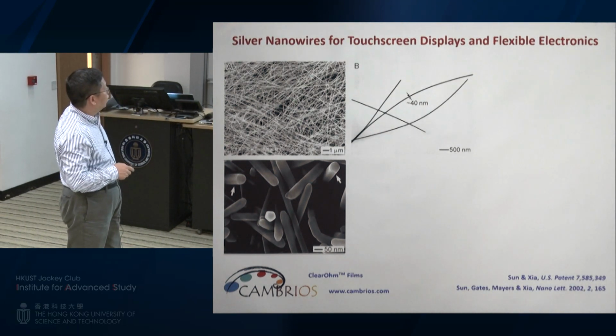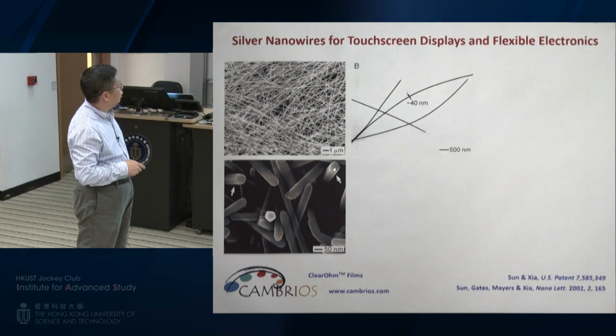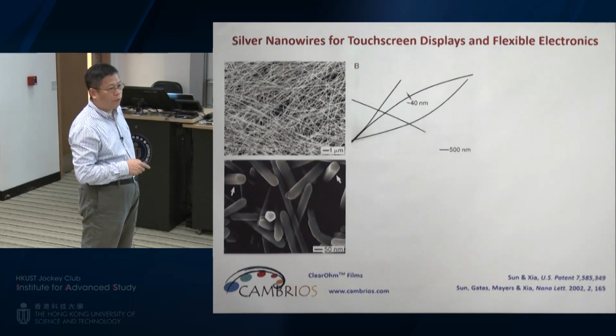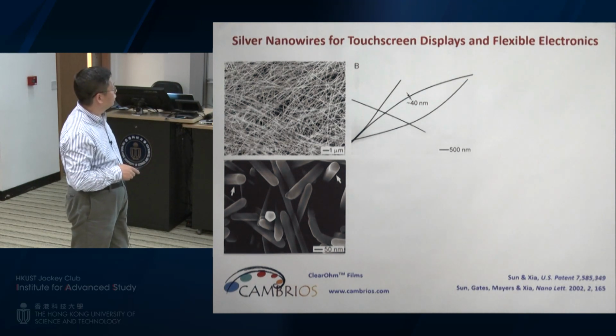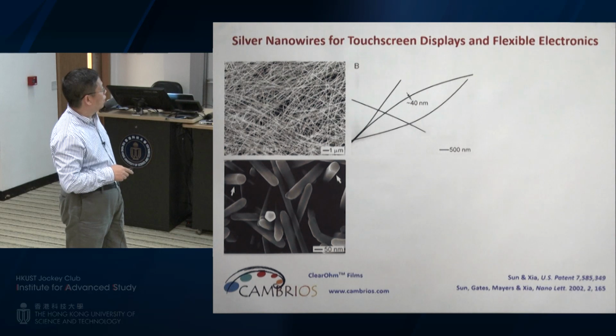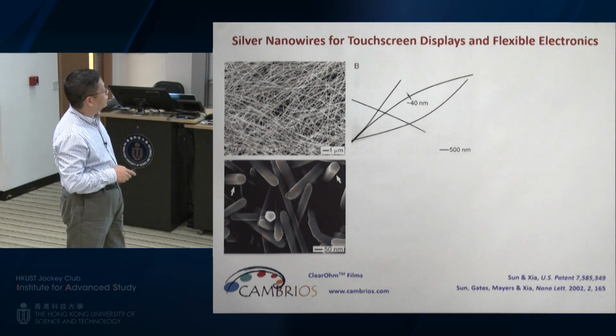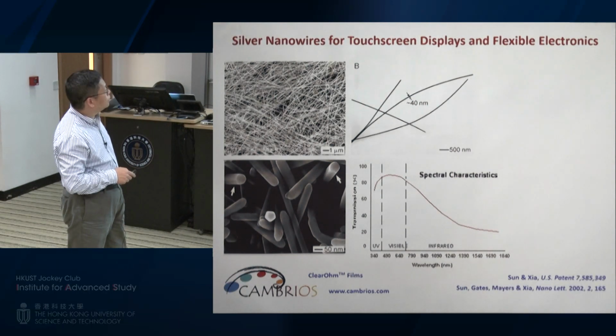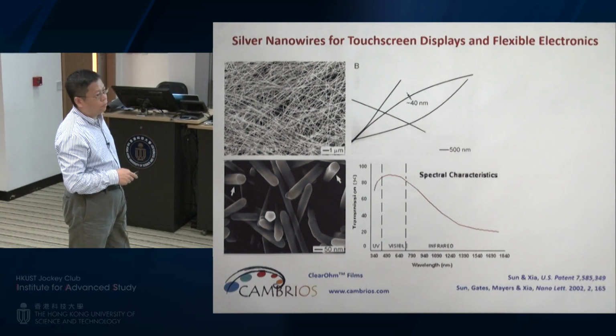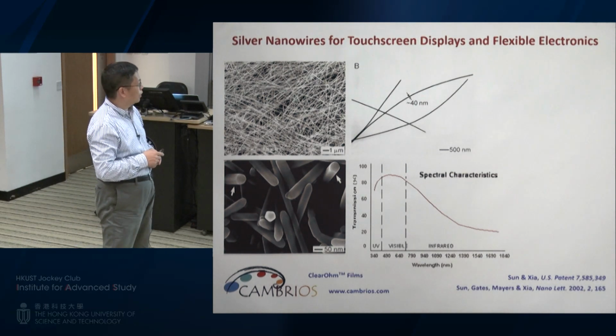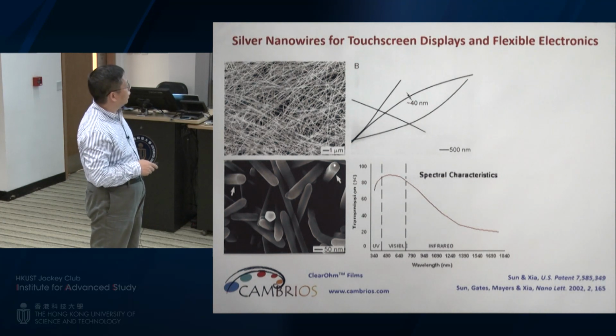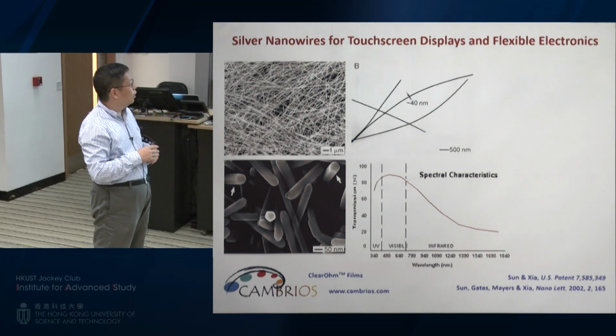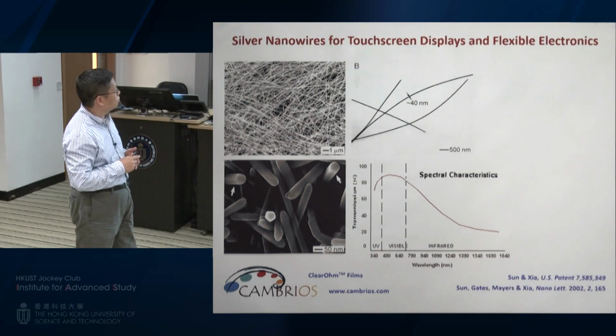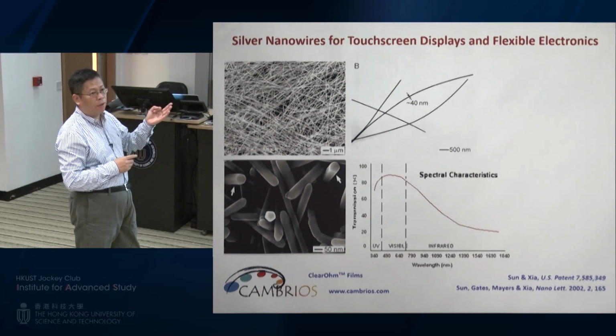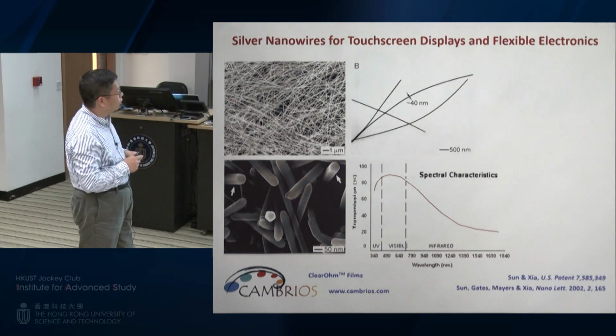And in that case, we can make uniform silver nanowires with diameters of about 40 nanometers. Nowadays, of course, we can push them further down to like 20 or 15 nanometers, with an even smaller diameter. And what's good about these silver nanowires? Well, when their diameter is so thin, they are going to have pretty high transmittance or transparency in the visible region. They don't absorb or scatter light in this region significantly. So when you mix these silver nanowires with a polymer and coat them onto another polymer substrate, you are going to make this substrate conductive, transparent, and flexible. So that's basically what we need for a number of applications.